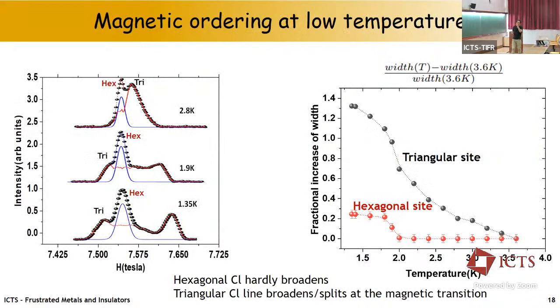This I will skip. And for NMR, now if we look at the NMR at low temperature, so this is at 2.8 Kelvin here. Actually, at low temperature, the line broadened, and we don't see anymore all the details I was showing, the splitting of the lines from the structural transition, etc. It's all smeared out. The lines have broadened too much, and now the spectrum is somehow more simple. We have again two broad lines, one corresponding to the hexagonal side and one to the triangular side. So these are these two, and both are overlapping also because they have broadened a lot. So the first peak is attributed to the hexagonal side and the second one to the triangular side.